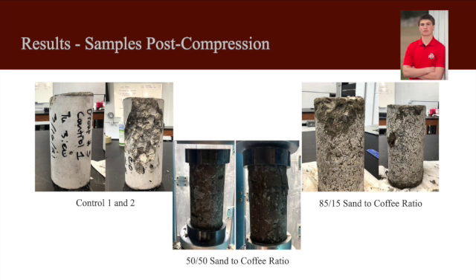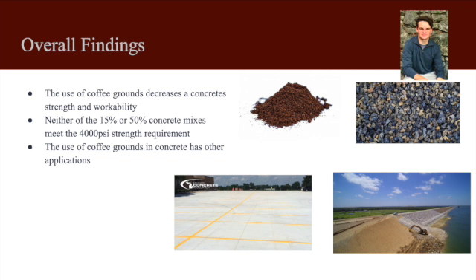In summary of the results, the coffee grounds negatively affected every single statistic that was measured for the purpose of our experiment. We found that as you increase the amount of coffee grounds used in replacement of fine aggregate sand, the workability and strength of the concrete will both decrease. So in other words, as you use more coffee grounds, the weaker and more brittle the concrete will become. The concrete will also become more viscous and harder to work with, so it won't flow as well when laying the concrete.